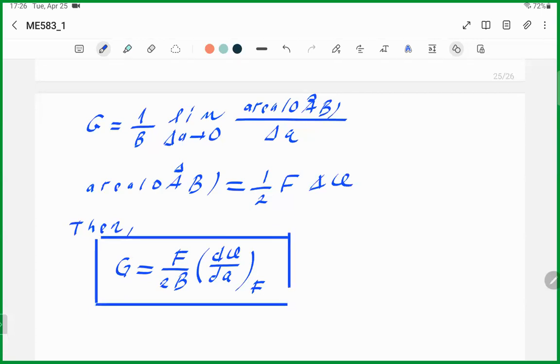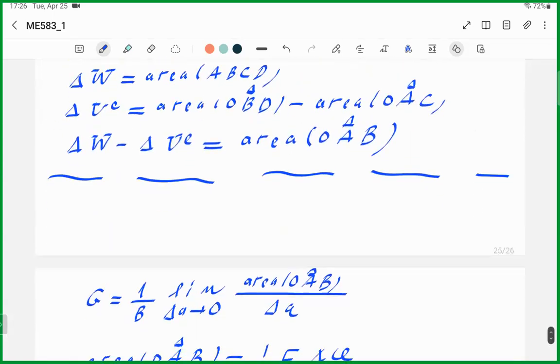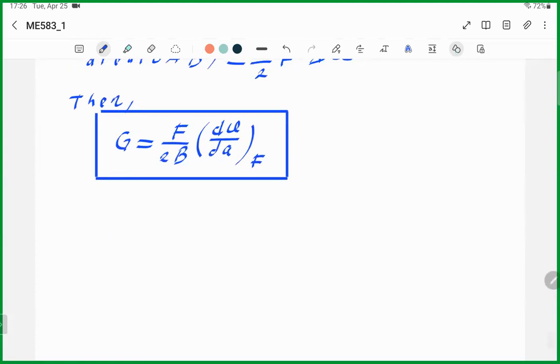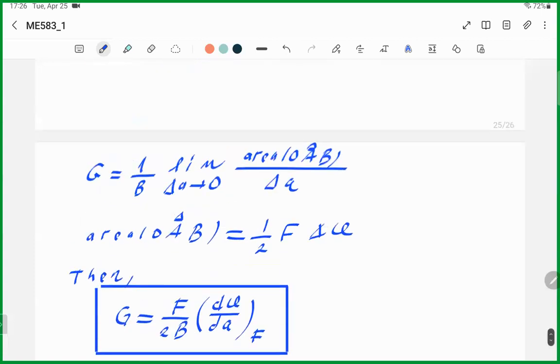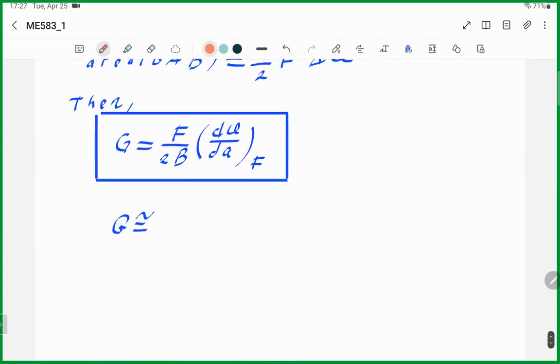For any given crack length, this is the energy available for fracture. It can be evaluated by a general expression. It's given as a general expression. And an approximation is used in fracture tests as an approximate result. You can use this. You see, we have the limit here, but area over B delta A, area of OAB divided by B delta A can be used if there is available data in fracture tests.